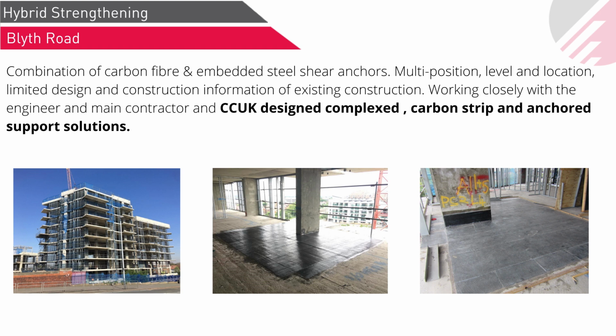So the issue there was that after the construction of these concrete frames, there are 3 concrete frames, as we could see on the leftmost image: one at the front, one at the back, and one on the left hand side. Those 3 frames were constructed in 2014. After the construction of these frames, the contractor working there went into administration. So before passing the work to the new contractor, there was some investigation work done, and they found that there was some reinforcement missing in the flat slabs, and there were around 385 plus areas where the reinforcement was not adequate as it should have been according to the design.